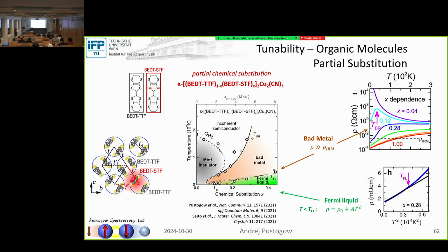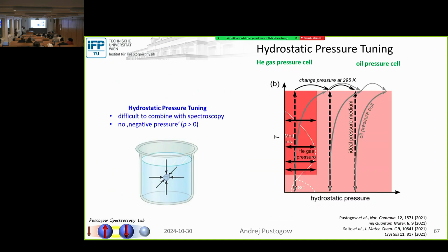So if you have a pressure cell which is focusing on high pressures, you don't have a very good resolution in the pressure. And therefore, it is useful to use these oil pressure cells, which cover a smaller pressure. And even also these helium gas cells are even more precise in the pressure resolution, because we want to have a lot of data points right around this range.